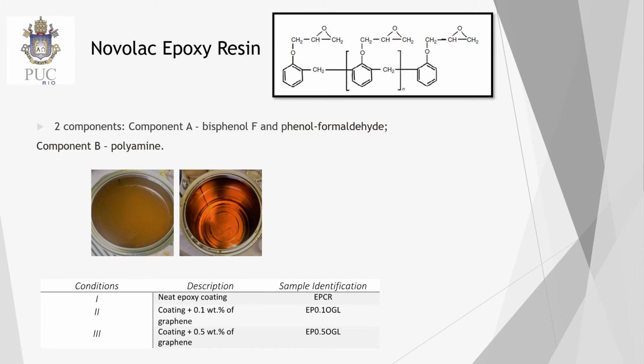The polymer coating deposited on the metal substrate was an epoxy Novolac base, manufactured by WAG Tintas, WAG Resin. In the specific case of this work, the company provided resin without solids, no fillers, and no pigments, so that the effect of the nanoparticles on corrosion tests could be studied in isolation. Coating component A consists of bisphenol F and phenol formaldehyde, and component B is a polyamine-based curing agent, as we can see in this slide.